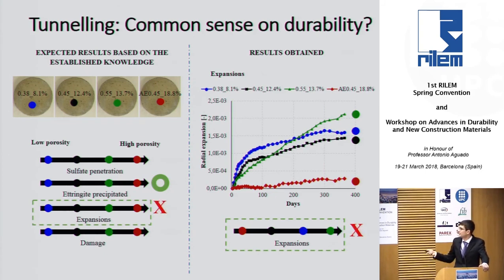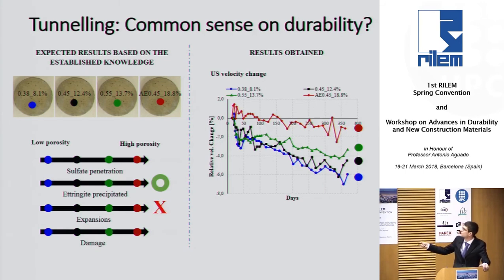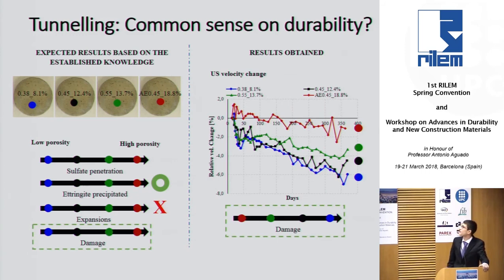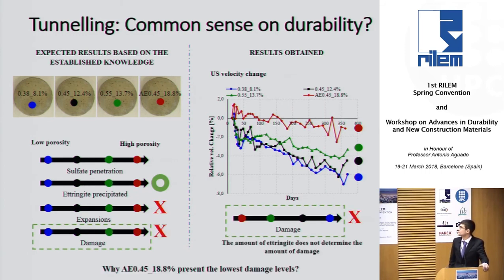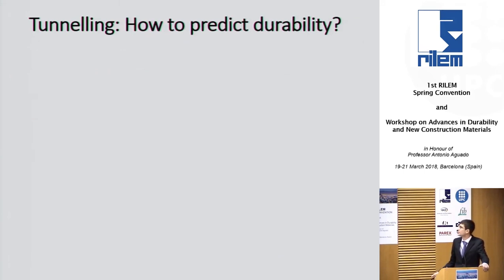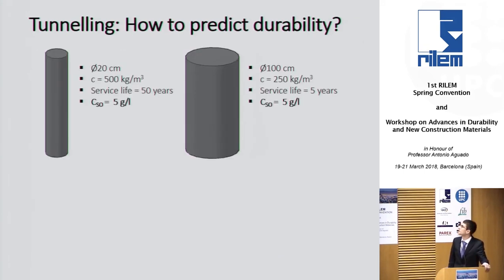So it's something that we have to take into account in terms of expansions or even damage. This is ultrasound measurement. You see, again, the damage is much lower because the reduction of ultrasound measurements is smaller for the more porous, the red one, mix, right? So we can have better performance by playing with the mix.